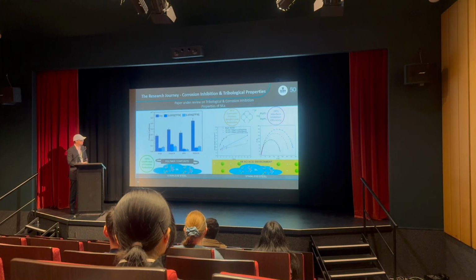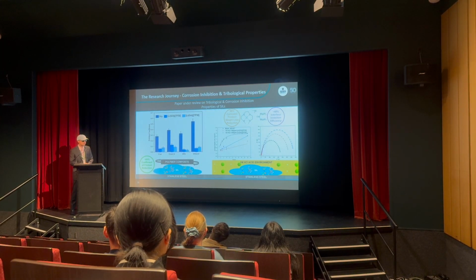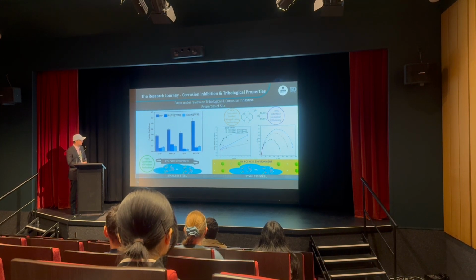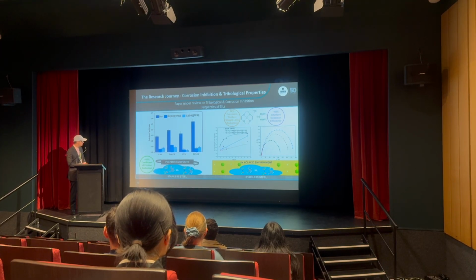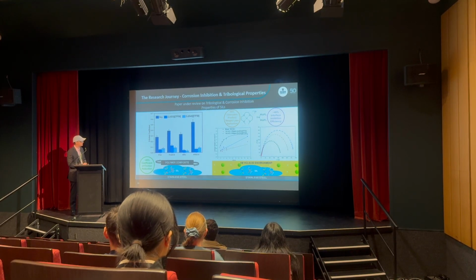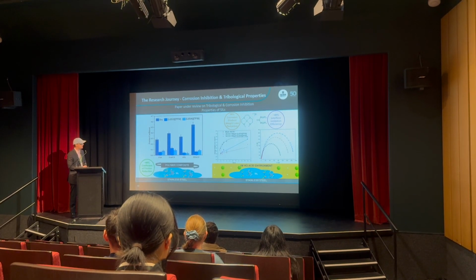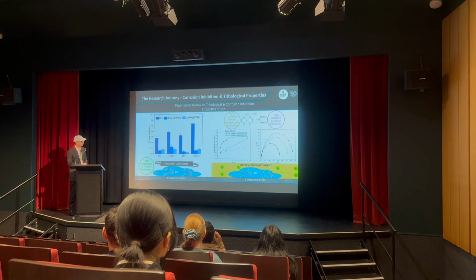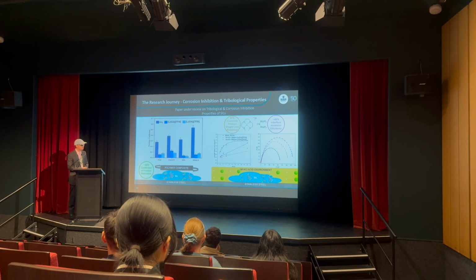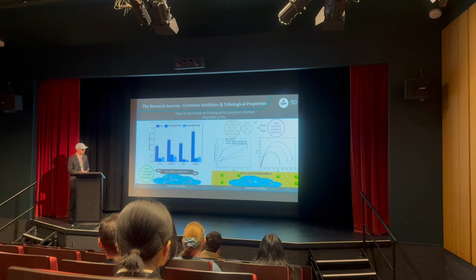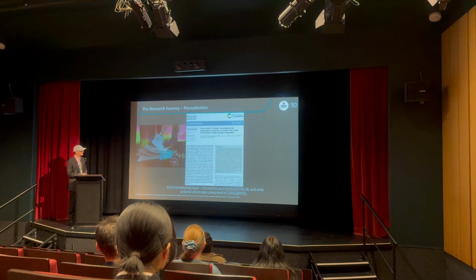And we've also applied Solvate Ionic liquids as lubricants, and as corrosion inhibitors. The key findings from this work were that they reduced friction by about 60% and corrosion by greater than 60%. And this was confirmed through weight loss testing and electrochemical impedance spectroscopy, EIS testing as well.